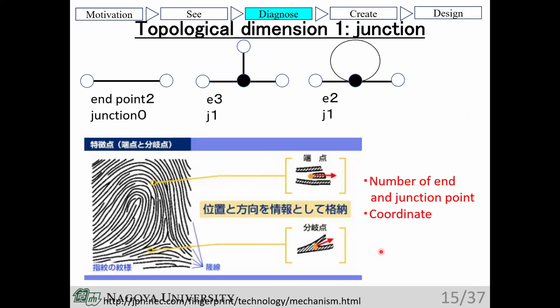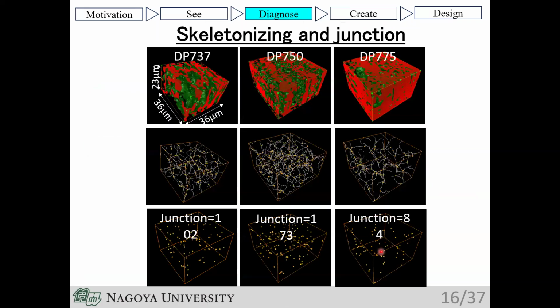Next, I will touch on connectivity and network analysis. That is very helpful to understand branching of the microstructures. To evaluate the entanglement of a matrix and the second phases, branching analysis typically used in biometric fingerprint authentication is highly effective. By recording the coordinates and types of endpoints and junctions, a complex network can be characterized. In the case of 3D dual phase steel microstructures, the thinning algorithm skeletonization revealed the underlying network of the second phase.